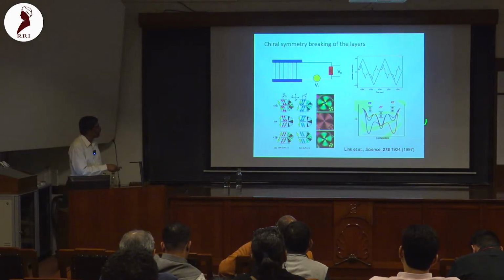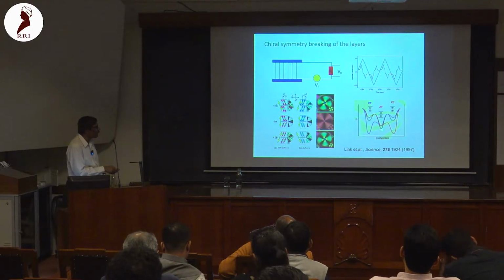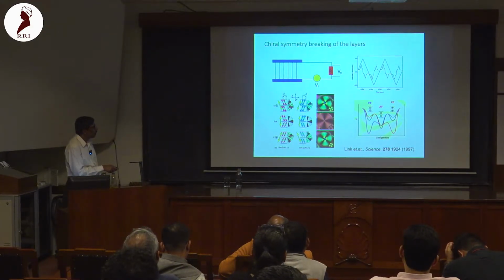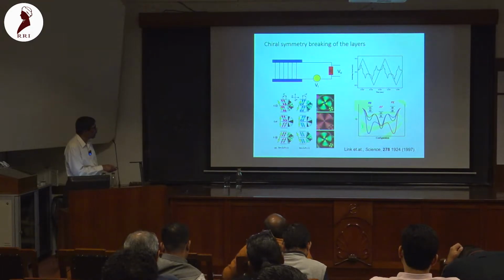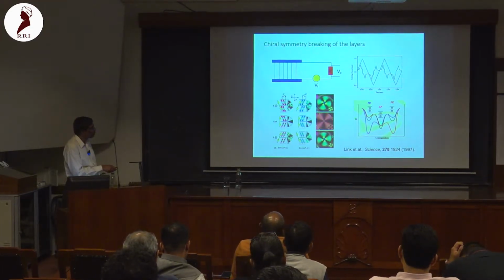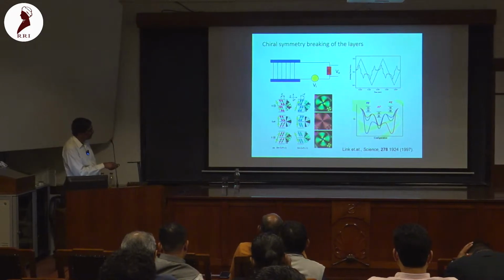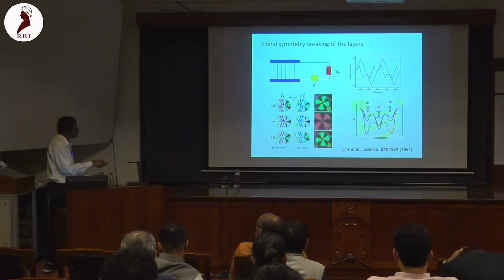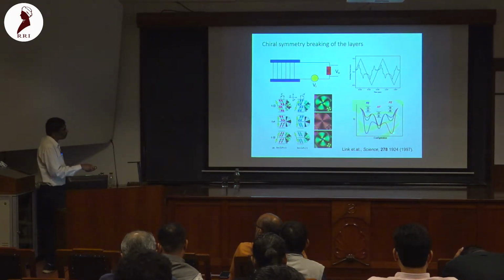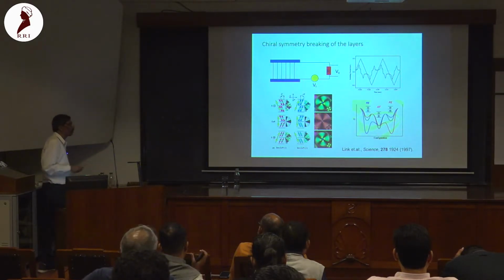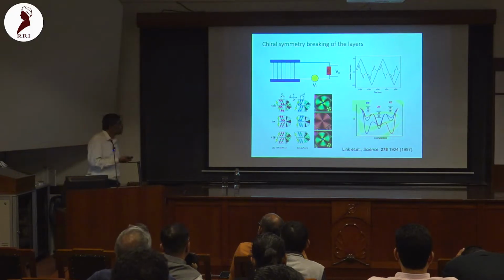So here, in this energy diagram, this black line shows that this is the antiferroelectric state, which is the ground state, and the other two states are metastable at zero field. But when you apply the field with one sign, this state becomes lower in energy, and the other two are metastable. When you change the field to the other direction, this red one becomes the lowest minimum, and the other becomes metastable. So using this,